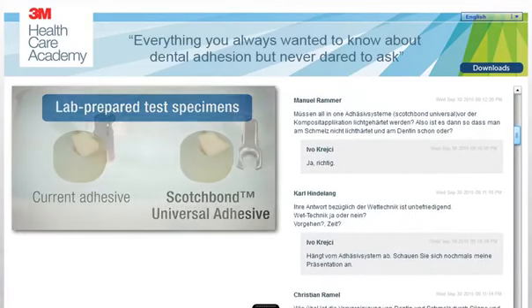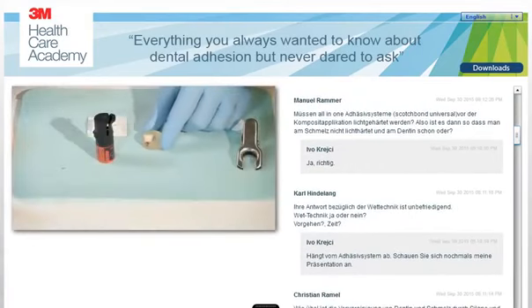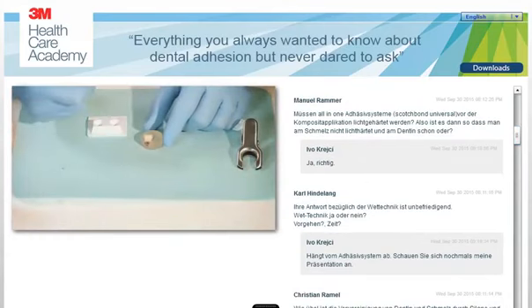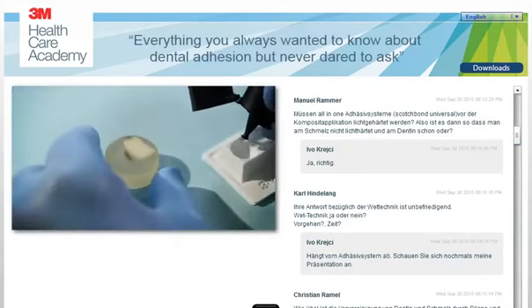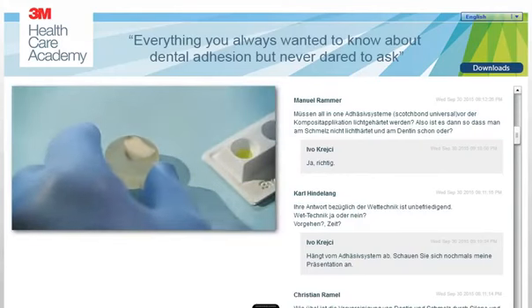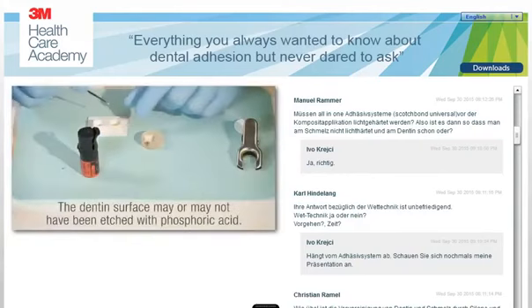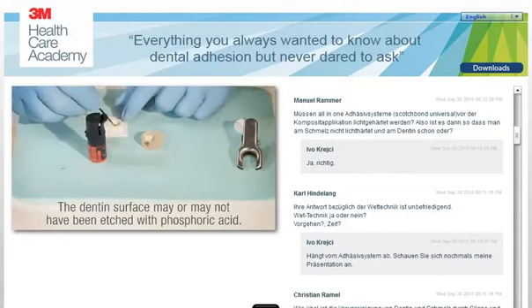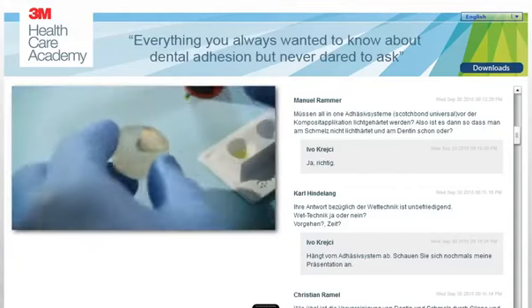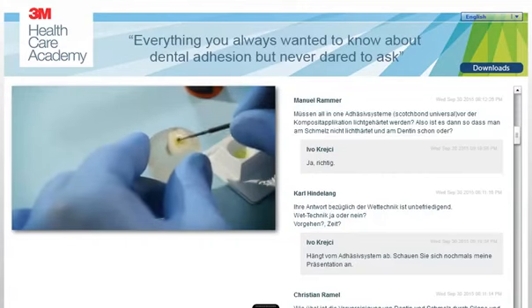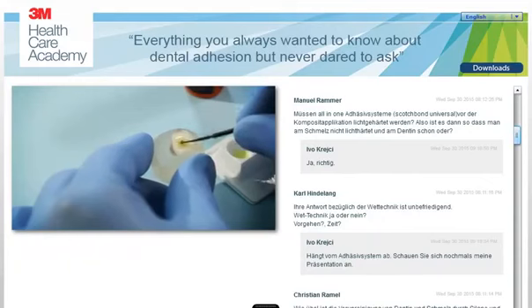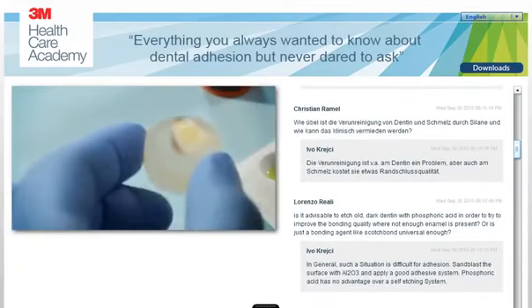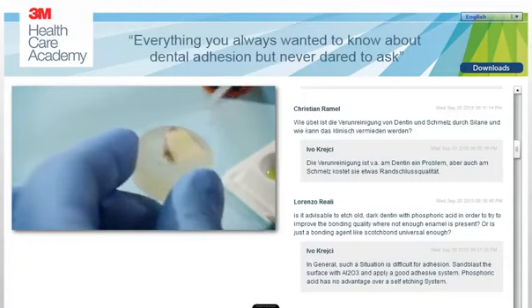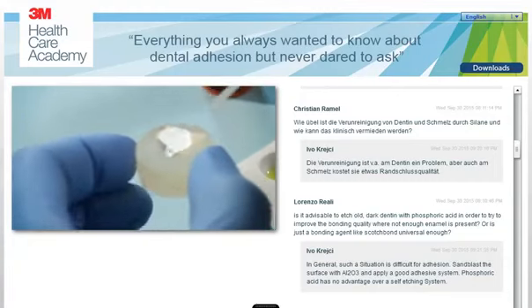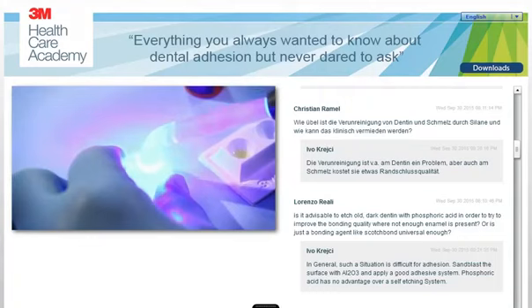To create the test samples, dentists first applied the adhesives to the exposed dentin surface, following the manufacturer's instructions for use. With Scotch Bond Universal Adhesive, the dentin surface may or may not have been etched with phosphoric acid, depending on the dentist's preference. Scotch Bond Universal Adhesive was then applied with a brush using a scrubbing motion for 20 seconds to assure uniform distribution across the surface and penetration down into the dentin. It was gently air-dried for 5 seconds to evaporate the solvents and produce a uniform film. Then it was light-cured for 10 seconds.